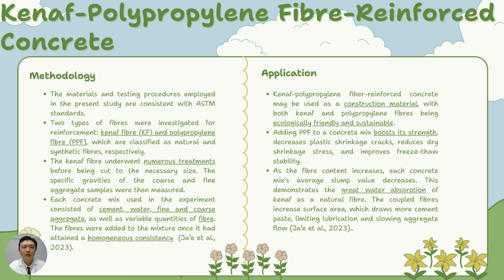The kenaf fiber underwent numerous treatments before being cut to the necessary size. Each concrete mix used in the experiment consists of cement, water, fine and coarse aggregate, as well as variable quantities of fiber. The fibers were added to the mixture once it had attained a homogeneous consistency. The application is that kenaf polypropylene fiber reinforced concrete will be used as a construction material, being ecologically friendly and sustainable. Also, the addition of PPF will boost the strength and decrease the plastic shrinkage. With the fiber content increase in the concrete, it demonstrates great water absorption as the kenaf, a natural fiber, absorbs it.